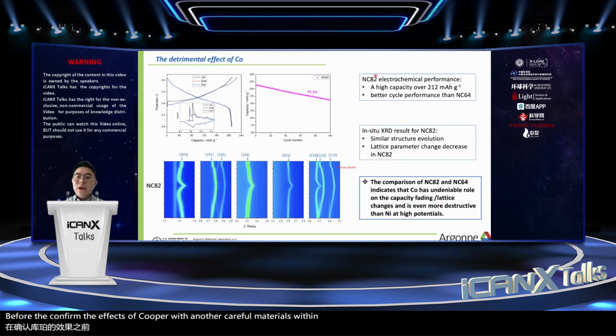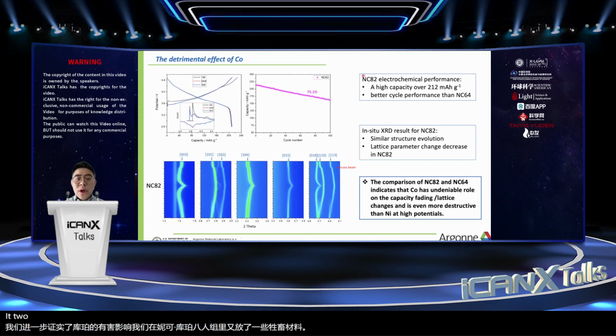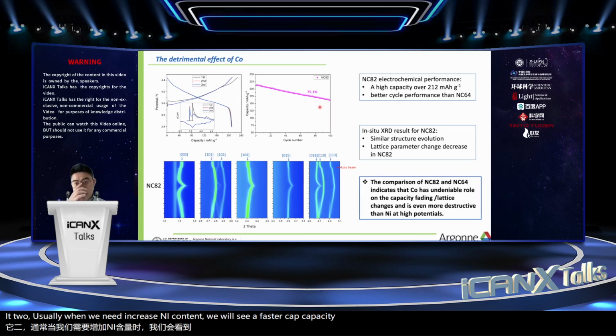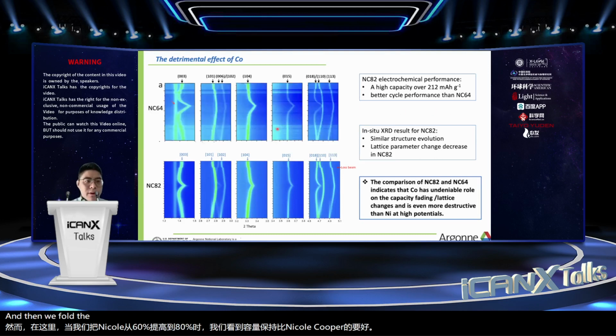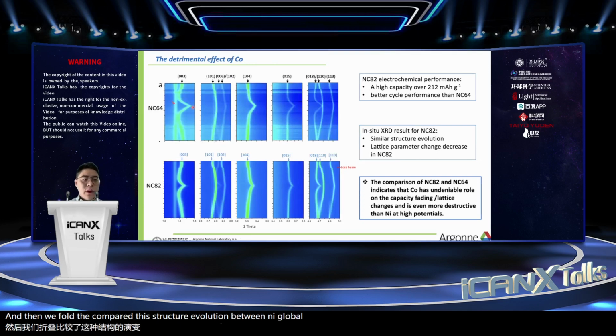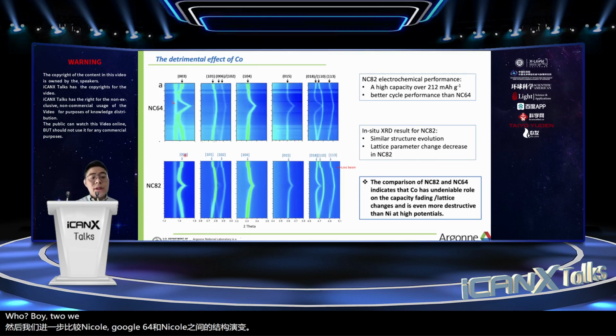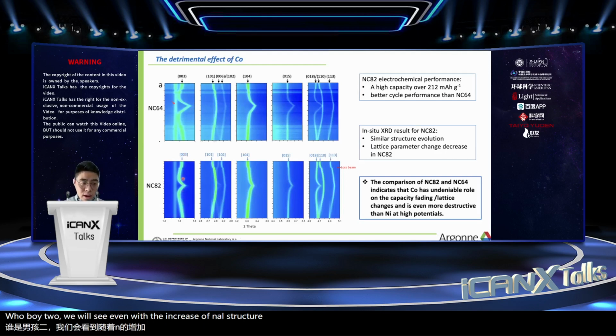We further confirm the detrimental effects of cobalt with another cathode material. We synthesize the nickel cobalt 82. Usually when we increase the nickel content, we will see faster capacity fading. However, here when we increase the nickel from 60% to 80%, we see the capacity retention get better than nickel cobalt 64. And then we further compare the structure evolution between nickel cobalt 64 and nickel cobalt 82, we will see even with the increase of nickel, the structure contraction still decreases.